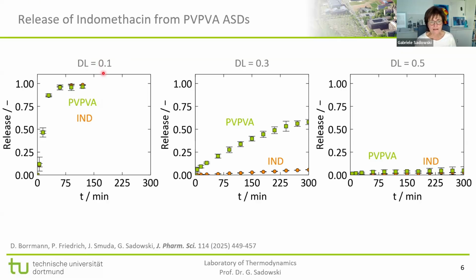So if we take such an ASD, where we have now a drug load of 0.3, that means 30% of indomethacin, and we do the same experiment, so we take this and we dissolve it in water, then we see that the release curves are totally different from this one. So what we see is that both PVPVA and indomethacin have a much smaller release as in this case. Even after 300 minutes, meaning after 5 hours, we are far away from the total release. So that simply means that the tablet didn't dissolve.